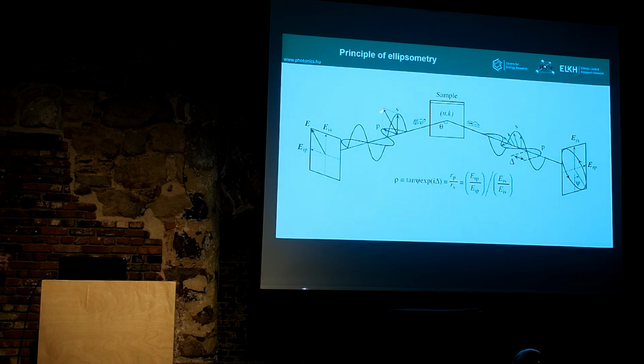So in ellipsometry, we measure the change of this polarization when the light is reflected, and mathematically it can be described by two components. The light is the oscillation of the electric field, and maybe you remember the Fresnel reflection equations, which are different for light where the electric field is parallel to the plane of incidence and perpendicular. In a general case, if you have linearly polarized light, which means that the electric field is oriented in one direction, usually after the reflection it will be elliptically polarized. So this is why the method is called ellipsometry.